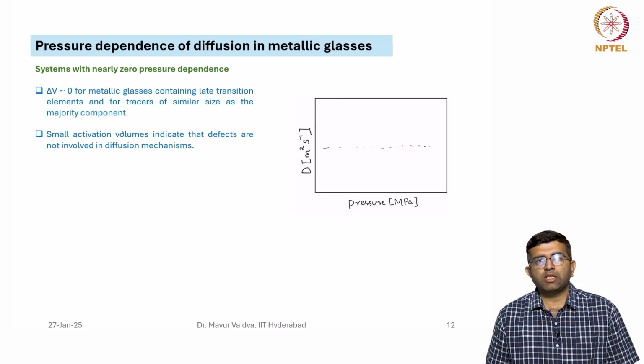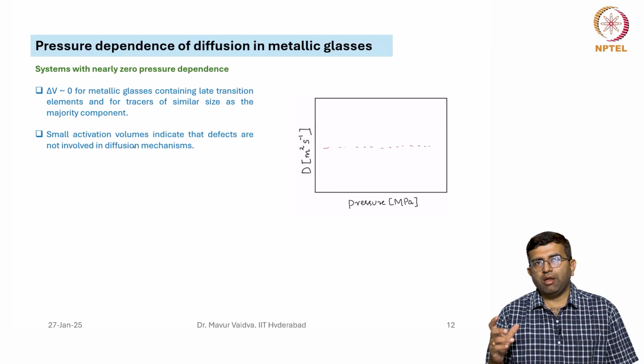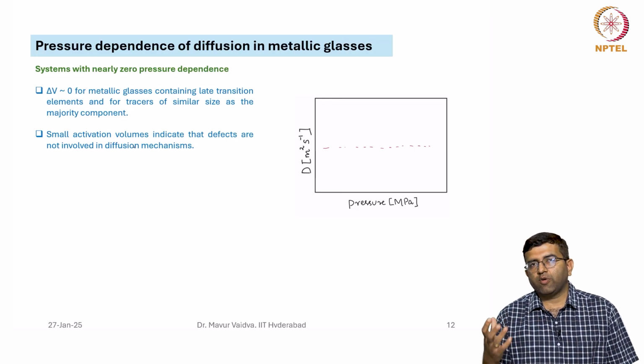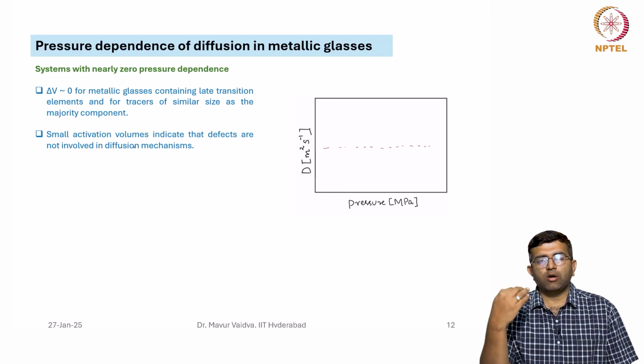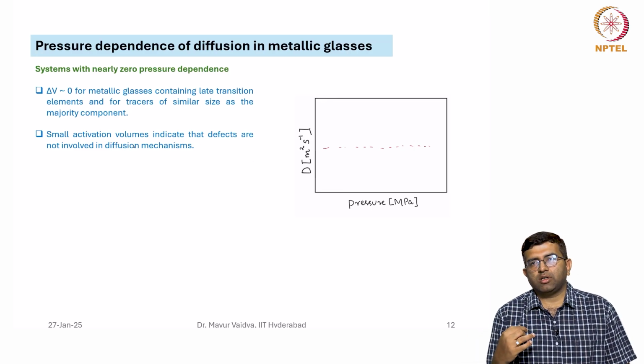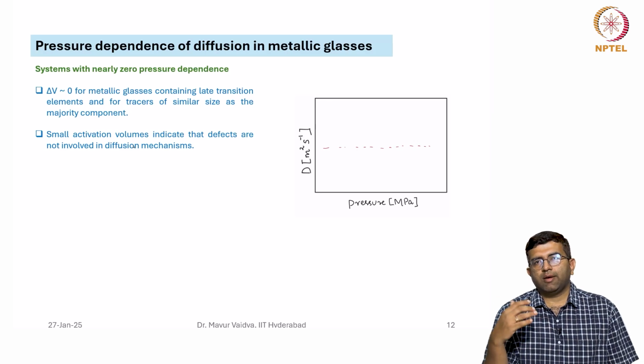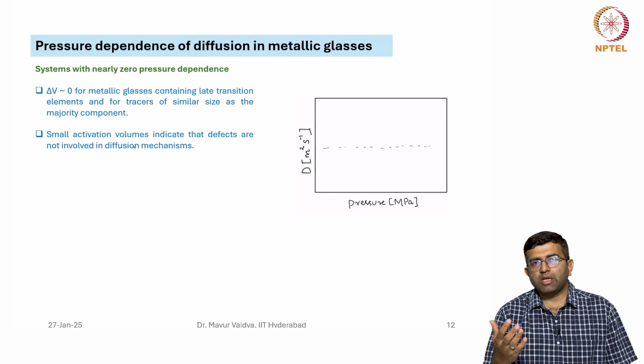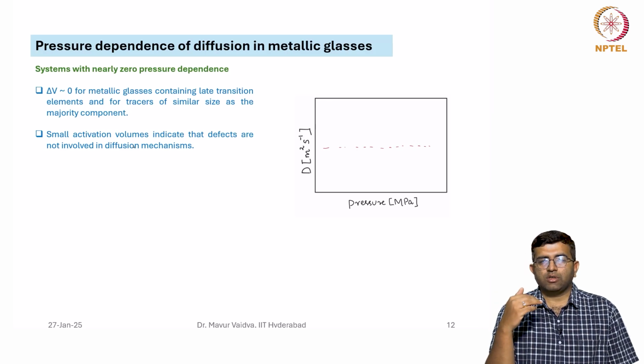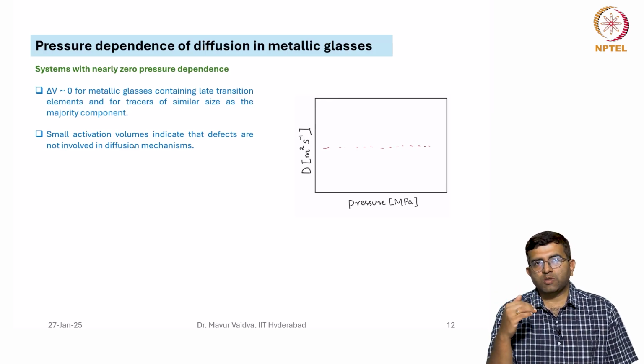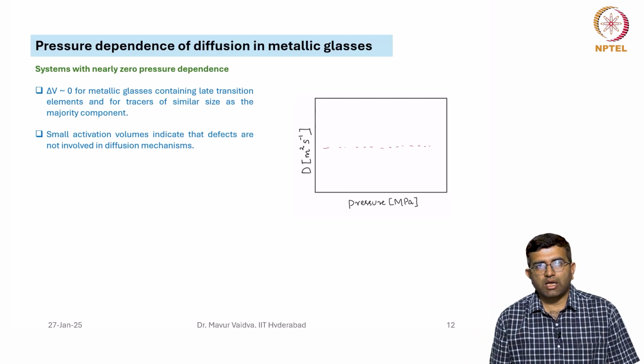In addition, the small activation volumes also indicate that defects are not involved in the diffusion mechanism, because we saw, when we were talking about the activation parameters for diffusion, that when it comes to the pressure dependence, the defects have a certain excess volume associated with them. Some are negative, some are positive. So when it is almost equal to 0, it indicates that the defects are not involved in this diffusion mechanism.